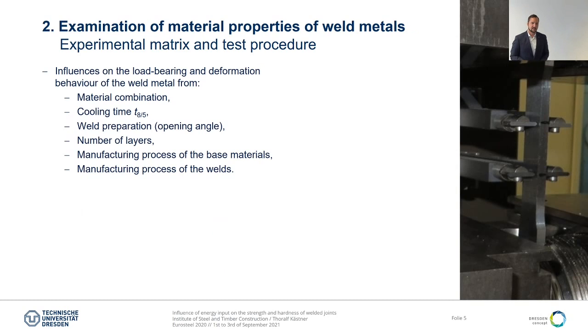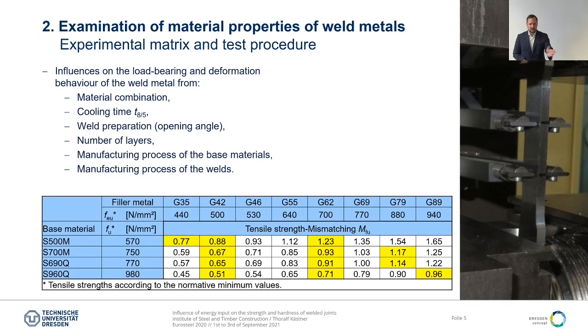So within our experimental test we covered a huge amount of influencing factors. You can see them here. One of the most interesting were of course the material combinations. We have here a table which summarizes the tensile strength mismatchings of the steels we examined. So we have an S500M up to an S960Q with a huge amount of filler metals. Those tensile strength mismatchings highlighted here were the material combinations we have examined within our experimental research, and as you can see we have an undermatching of about 50%, but also overmatchings up to 23%.